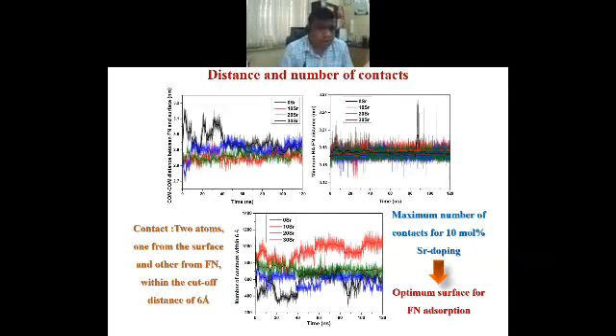When we did several experiments with different levels of strontium doping, up to 30% doping in hydroxyapatite, we saw some non-linear trends. At 10 to 15% doping content, we saw that better cell adhesion is promoted and cell proliferation is facilitated. We are trying to address this intriguing observation, to understand what the basis is for such observations.